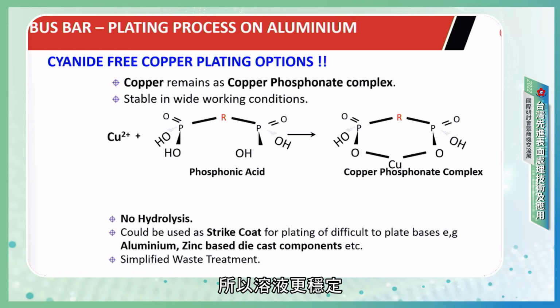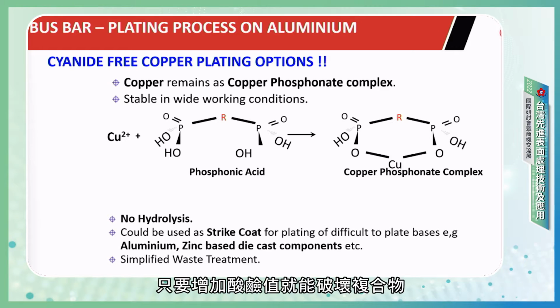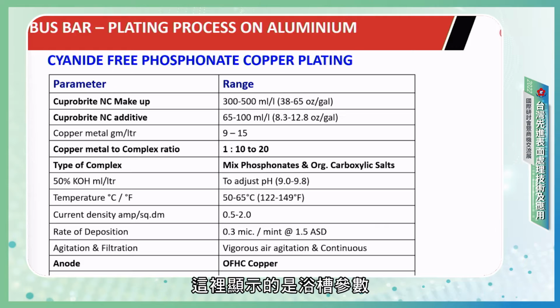So the solution is much more stable and provides a sustainable strike coat for aluminium and/or zinc-based die casting or MS components. And the waste treatment is also very, very easy. You just have to increase the pH, and the complex gets broken, and subsequently we can precipitate copper from the solution. This is the bath parameters shown for our subject process.